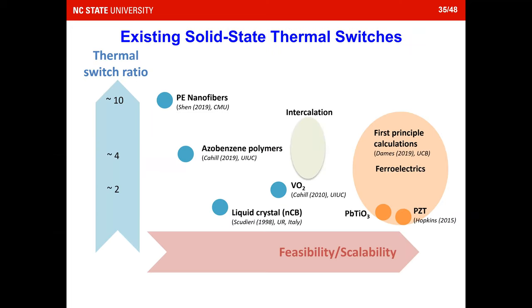So if you look back at the existing solid state thermal switches, there are different types of thermal switch in the history. There are some materials with a very high thermal switching ratio, about 10, but it's not very feasible. You just use a fiber, so it's very hard to apply to a broad range of applications. There are also polymers using a light. They can have transformation, but that actually isn't solid. It's also not very applicable for all kinds of solid applications. There are also liquid crystals.